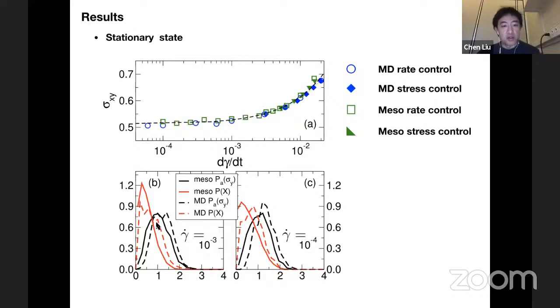The MD data is shown by the dashed curves, and the meso data is shown by the solid curves. They are not perfect in this case, but they're comparable. And it seems that the meso model has a systematic deviation to smaller values of these quantities in the distribution. This could actually be rationalized by the fact that in the MD simulation, the way that we measure local stress is not perfect. Because of technical issues, the values of local stress can actually be overestimated a little bit.